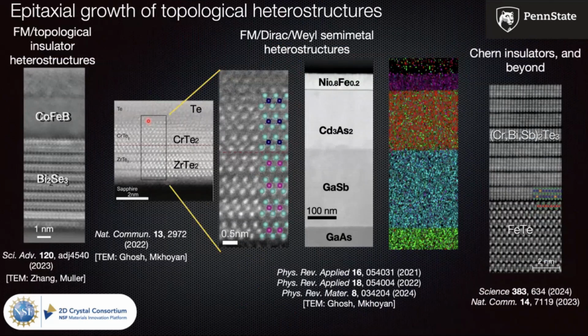Now, what kind of materials have we produced from this facility? Well, here's some examples. As I said, we've been very interested in spintronics. So the idea of taking a ferromagnet like cobalt iron boron, interfacing it with bismuth selenide. We've done 2-dimensional ferromagnets like chromium ditelluride, and interfaced them with Dirac semimetals like zirconium ditelluride. In my own MBE system, we've also grown Dirac semimetals like cadmium arsenide. And then, a very strong component of our research, of course, are Chern insulators or quantum anomalous Hall insulators. But we've sort of been taking that beyond the conventional idea of simply growing a quantum anomalous Hall insulator.